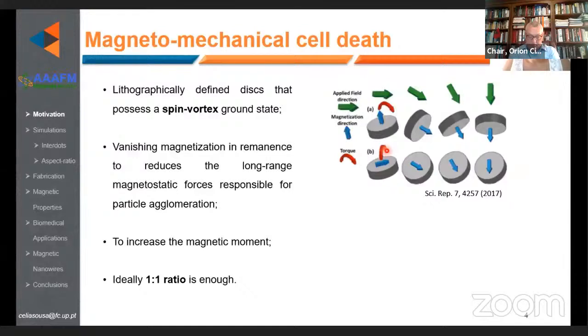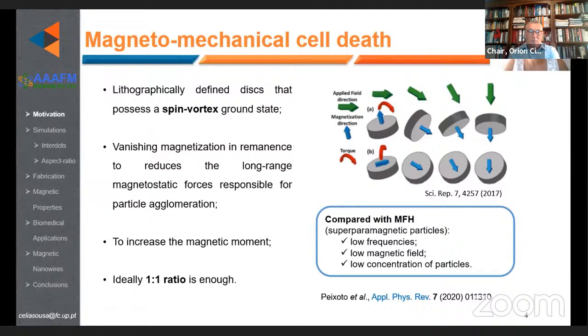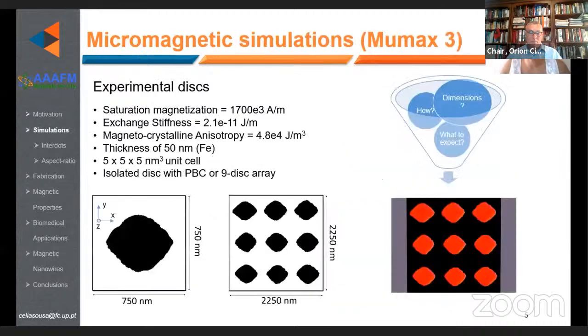Nanodiscs obtained by lithography techniques, defined in a micro and nanoscale, that possess a spin vortex ground state usually present a high magnetic moment when compared with superparamagnetic nanoparticles, and also present zero magnetization in remanence, which reduces the long-range magnetostatic forces that lead to particle agglomeration, which is one of the main disadvantages for biomedical applications of these nanoparticles. Also, compared with magnetic fluid hyperthermia, vortex nanodiscs can work at low frequencies, low magnetic fields, and low concentrations of particles. Ideally, only one disc per cell is enough to perform the cell death.